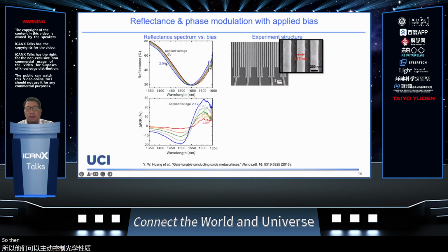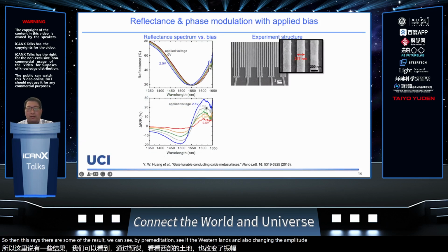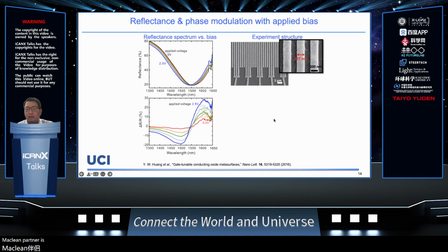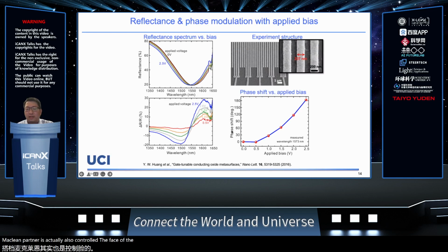This is some of the result you can see by applying voltage. You can shift the resonance and also change the amplitude by around 30%. But quite importantly, we are also controlling the optical phase. You can see that by applying voltage, you can change the phase by 1 pi here. This is quite an important demonstration, because we show that we can control phase and amplitude, which is exactly what we need as a tunable metasurface.